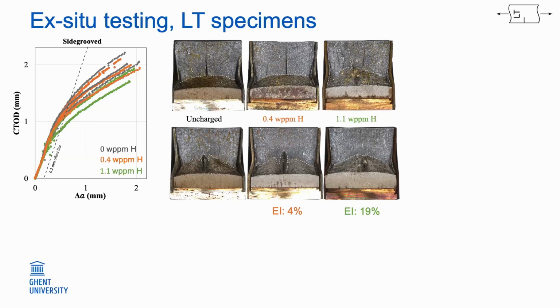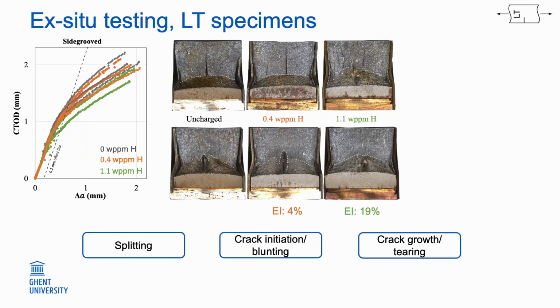And I put here some embrittlement indices just to show you a bit the very well-known effect of the hydrogen concentration. But mostly for these specimens, I want to focus on the three influences, which was splitting, crack initiation and blunting, and the crack extension or the tearing region, which was all influenced by hydrogen.